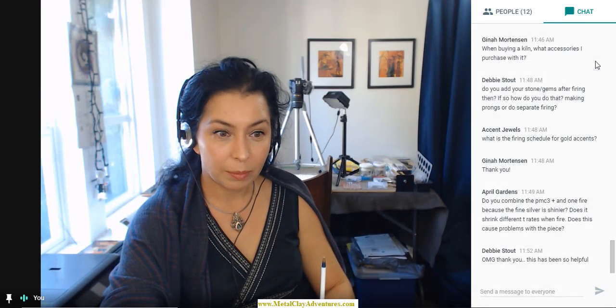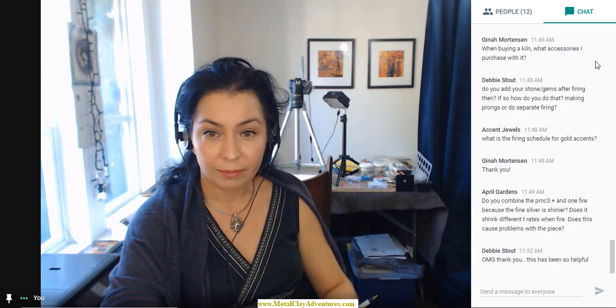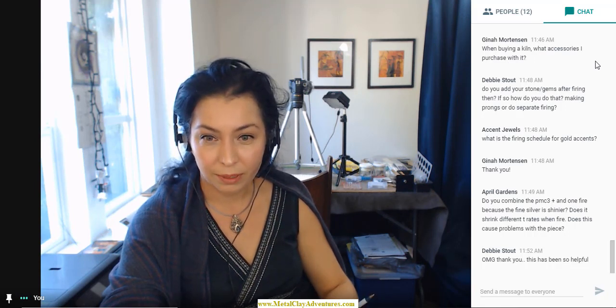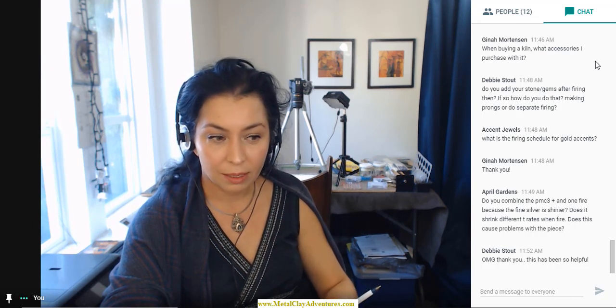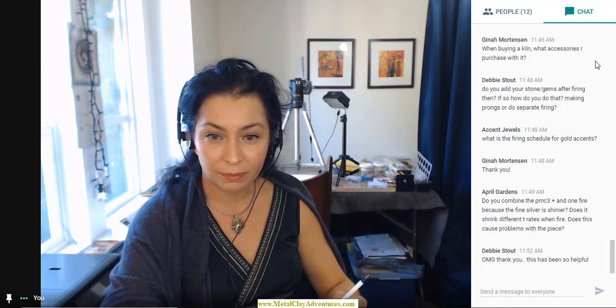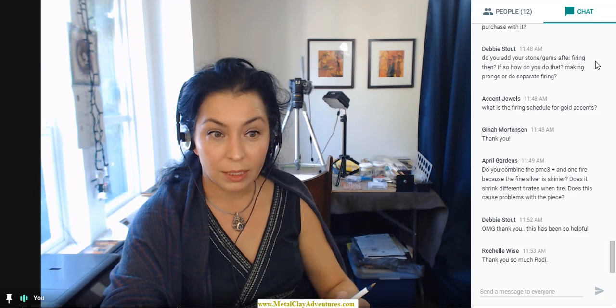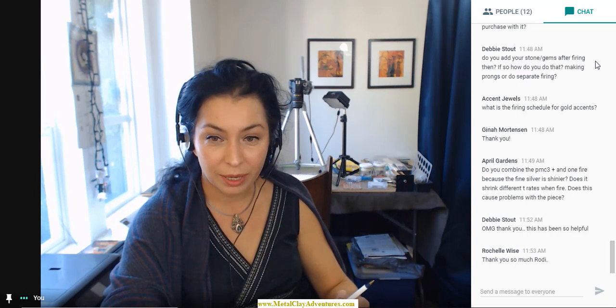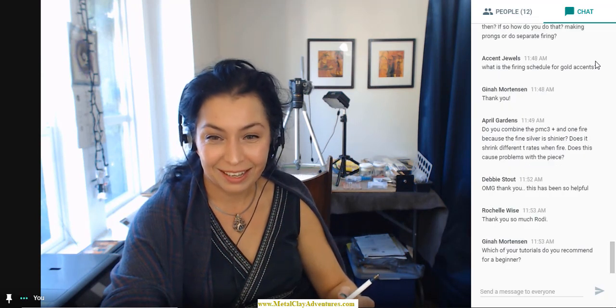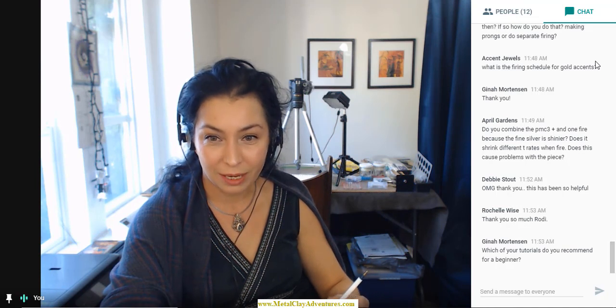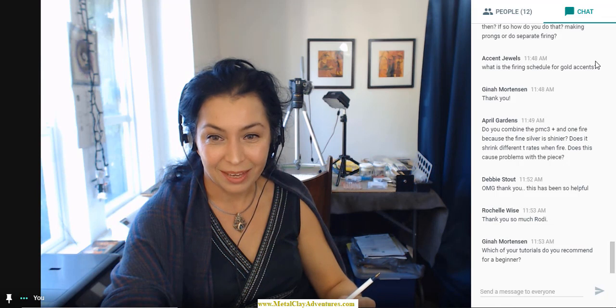April is writing. Do you combine the PMC 3 and 1.5 because the fine silver is shining? Does it shrink at different rates on fire? Does this cause problems with the piece? Yes, I'm combining PMC 3 and PMC plus with PMC 1.5 when I want harder metal for the base. I can do it in pendants, and I am doing it in rings, and I can do it in bracelets. Does it shrink different? PMC, no. This brand particular, no. I didn't have my pieces deformed. And that's amazing because they have a different shrinkage rate. You know that PMC 1.5 is 20%, and PMC 3 and PMC plus is 12%, but they didn't deform. And I'm using this trick a lot.